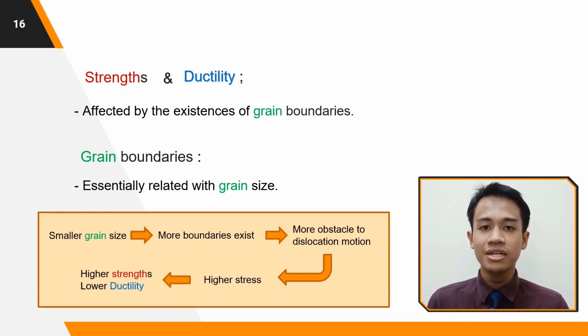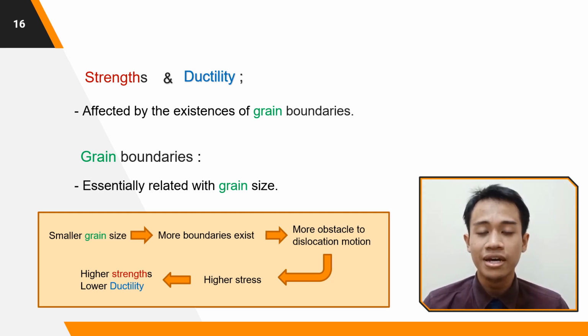As for strength and ductility, they are all affected by the number of grain boundaries. Grain boundaries are essentially related with grain size. The smaller or the finer the grain size is, the more boundaries will exist. Thus, higher stress is required to cause plastic deformation, and as a result, the strength will become higher. But in contrast, the ductility will get lower.